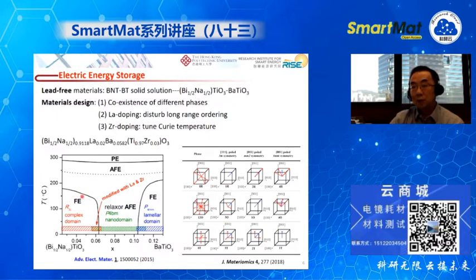The solid solution can have different phases, such as the ferroelectric phase, when the barium titanate has only a very small amount, and it can also have antiferroelectric phases when the barium titanate composition is ranging from 6 to 10%. So as we just discussed, the composition we chose is very close to the phase boundary between the ferroelectric and the relaxor antiferroelectric phases.